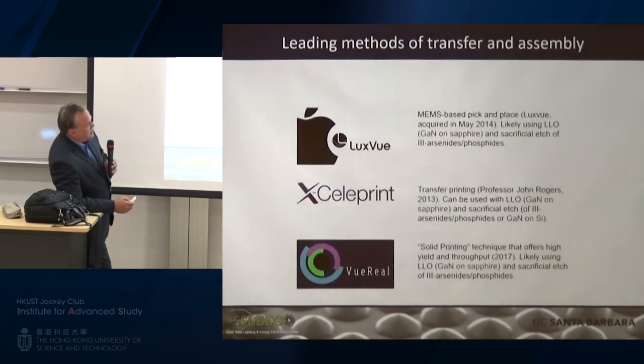So these are what I'd call the leading companies in the U.S. on this transfer and assembly approach. Just kind of point out where they're at. So Apple apparently still is using a MEMS-based pick and place. We're more along the lines of what I call transfer printing, and this was pioneered initially by John Rogers at Northwestern. It can be used with either PEC or laser liftoff, but I've heard recently they've gone now to PEC etching because it's less damaging. VueReal is a Canadian company, recently got a lot of funding, I've heard, and in their technique, they're doing a solid printing technique that gives a high yield.